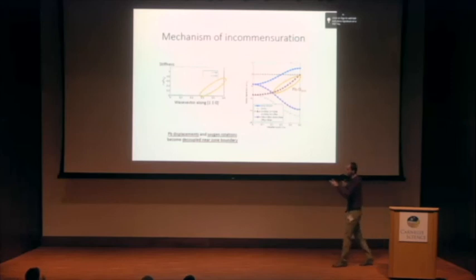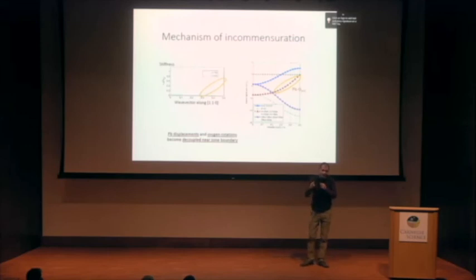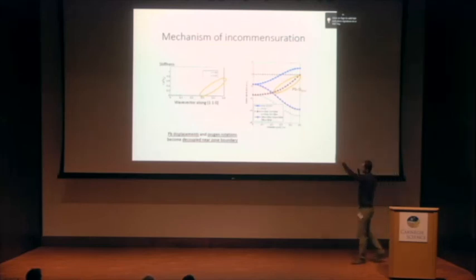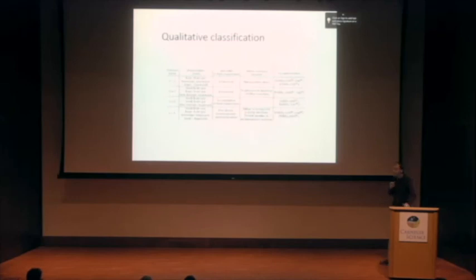And then why does it become positive? Because the fields that cross-amplify the dipole patterns in lead and in oxygen sublattices diminish on going towards the zone boundary. This is not due to the model, this is due to symmetry. So by simply analyzing the Coulomb terms, it is easy to understand why the predictions of the model are like they are. And this is some simple classification of perovskites with respect to their instabilities and diffuse scattering.